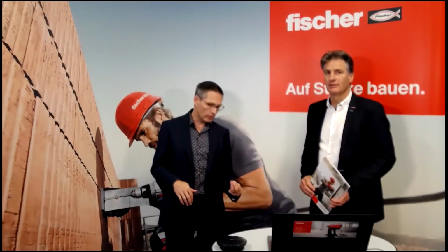which is not possible for post-installed anchors, for example, because you don't know exactly where the rebar is, and the concrete cone starts relatively deep in the concrete. At the end of the embedment, usually, if you look, for example, at a headed stud or a friction-based system like a through bolt or a bolt anchor. And there usually you don't have enough reinforcement, and not really the reinforcement where you need it to cross the cracks of your concrete cone. And for that, you rely really only on the tensile capacity, which is a conservative assumption. And then in special cases, you can utilize also your reinforcement. That's very rough and very general.